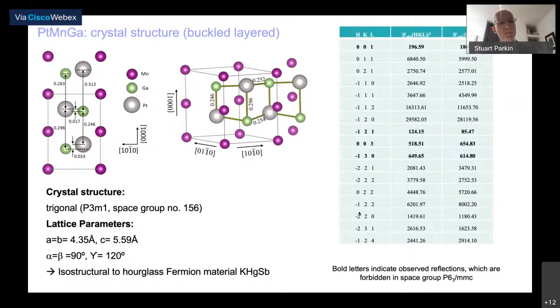platinum, manganese, and gallium successively, basically a layer of manganese moments, which is magnetic, separated by a layer of platinum gallium, but the platinum gallium layers are rumpled. So we actually have a very beautiful structure, platinum manganese gallium, and this gives rise to this Dzyaloshinskii-Moriya exchange because of this broken symmetry.